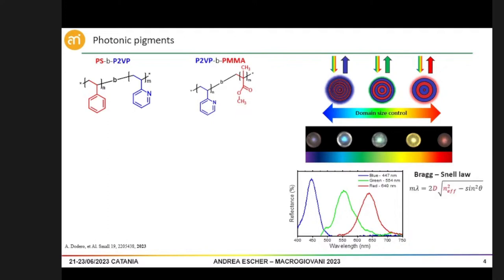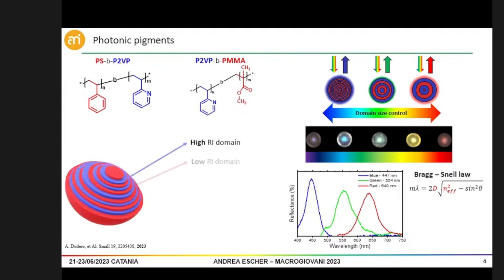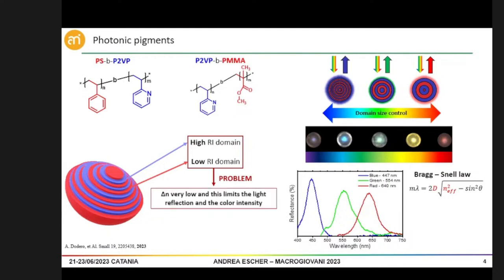The position of the photonic band gap is linked to the Bragg-Snell law, in which we have some different parameters, for instance, the domain size or the effective refractive index of the material. In our pigments, we have two different materials, one with high refractive index and the second one with low refractive index. But in that case, we have a problem, and the problem is that the dielectric contrast is very low, and so the idea is to increase the dielectric contrast using a hybrid particle.